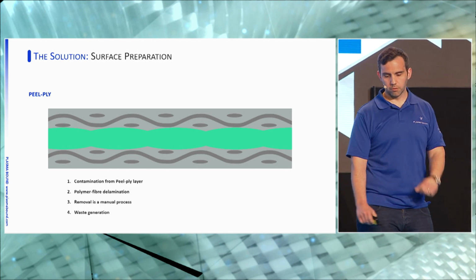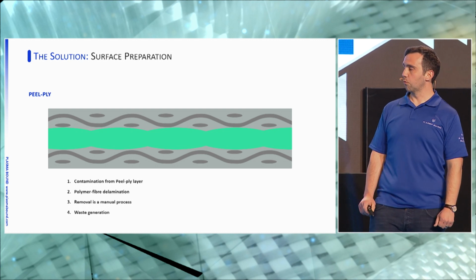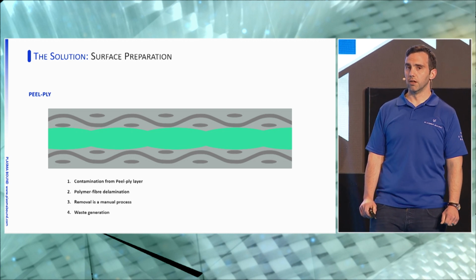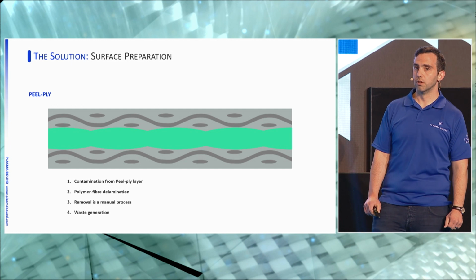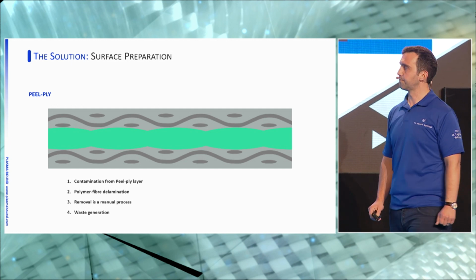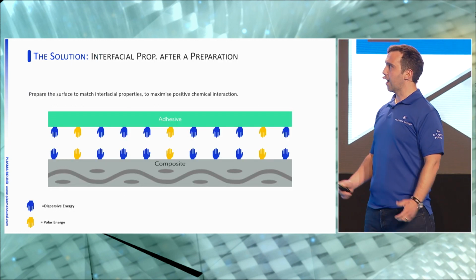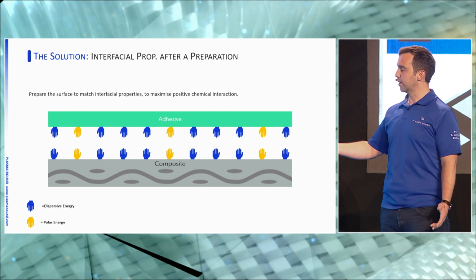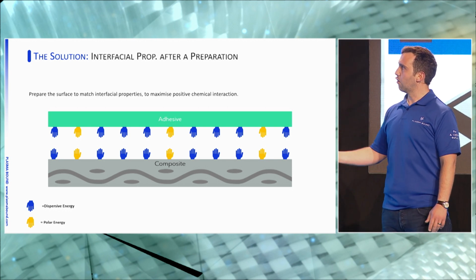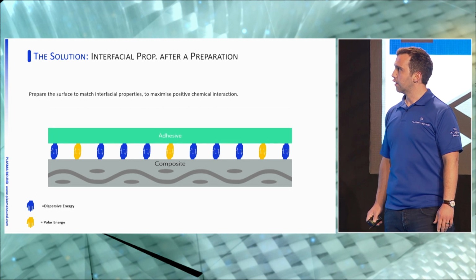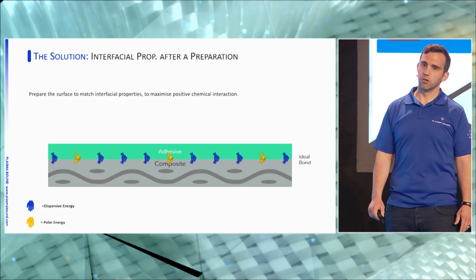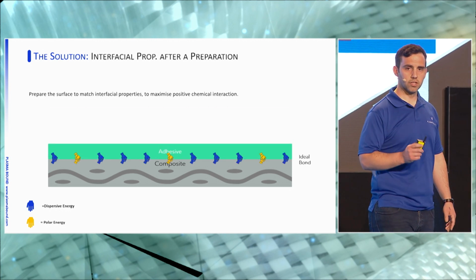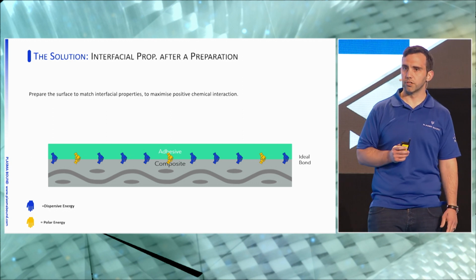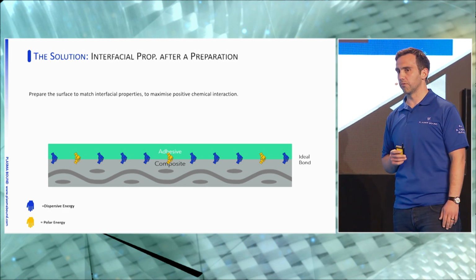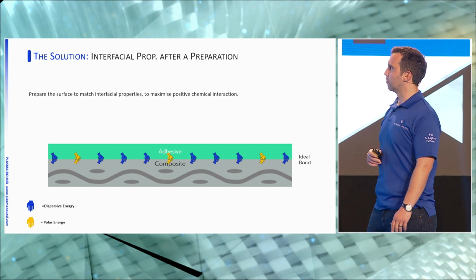However, and it's very important to point out, all of these techniques, when done absolutely perfectly, are very good at doing what they need to do: prepare your surface for bonding. And then after you've done all of this, what you end up with in an ideal world is all of the handshakes agreeing. And you should end up with, if you've chosen the right adhesive for the right substrate and done the correct pre-treatment, even if it's a complicated substrate like a PEEK unit, an ideal bond.